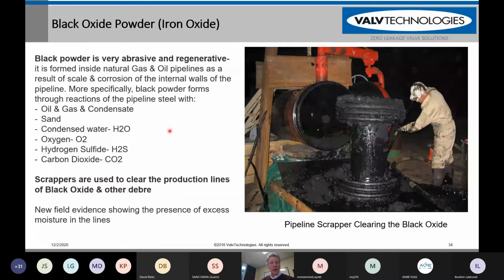You can see here a pig receiver that's been opened, and it has a lot of black oxide mixed with high viscosity oil. Black powder or black oxide is a result of oil and gas condensate mixing with sand, and then the rust and scale, which is forming inside of the pipeline, especially if you have any amount of water that can condense inside the pipeline. That water mixes with the oxygen, the hydrogen sulfide, and the CO2, and it forms that black oxide. That black oxide is very, very abrasive.